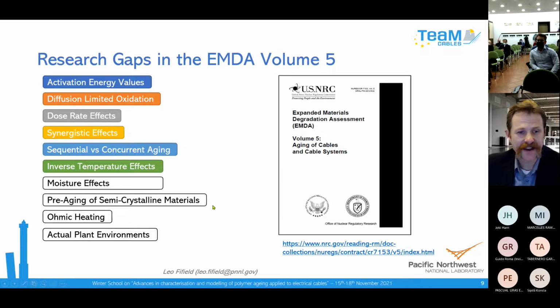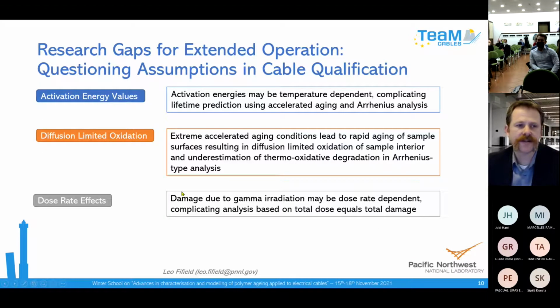All right. So let me just describe some of these knowledge gaps. One of the questions is about activation energy values. The way you put 40 years of age on a cable before you test it is, if the main degradation pathway is thermal degradation, you can just apply a higher temperature and it ages faster. You use an Arrhenius process to calculate how many equivalent years it represents when you do that laboratory aging.